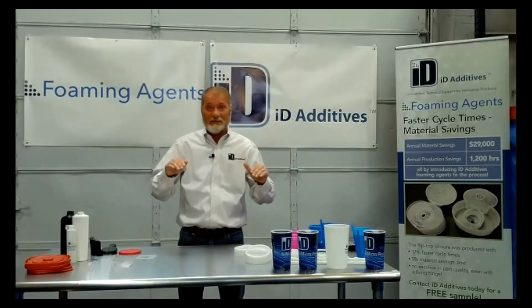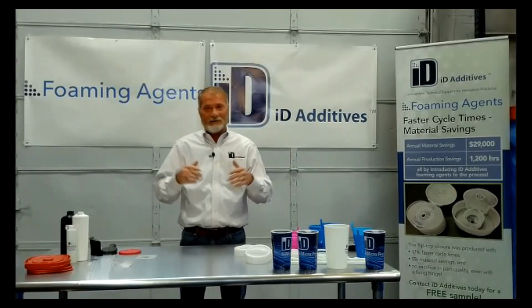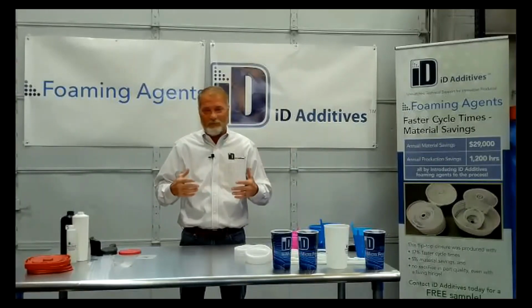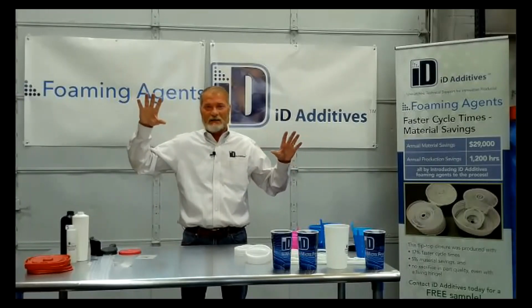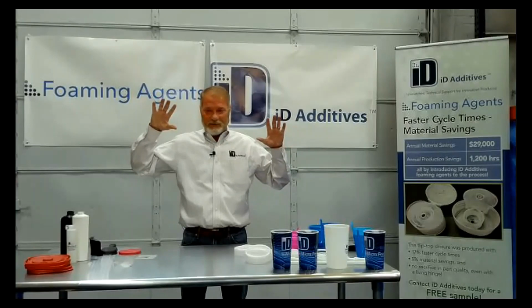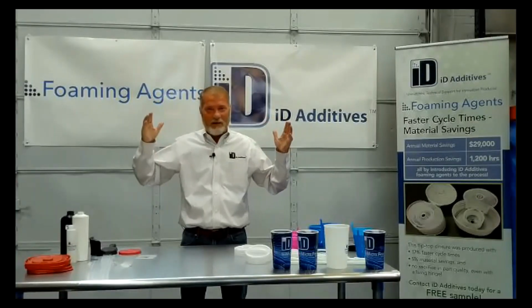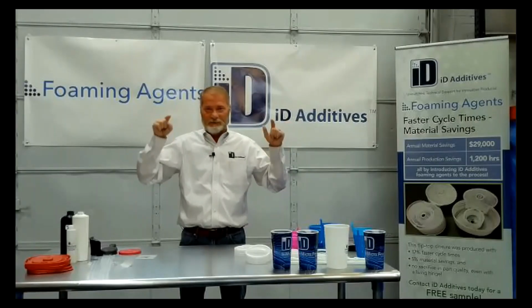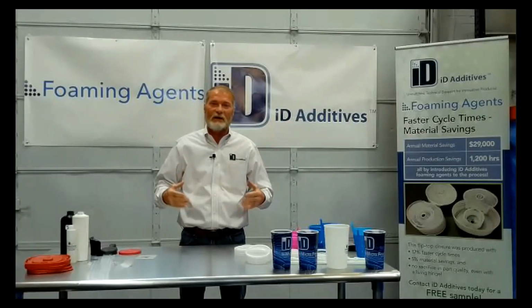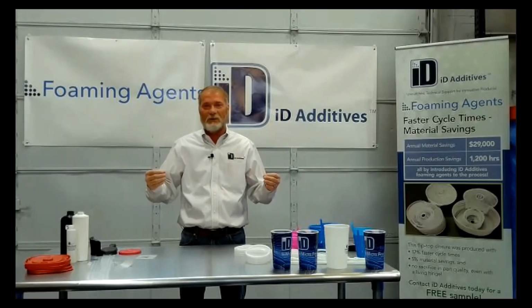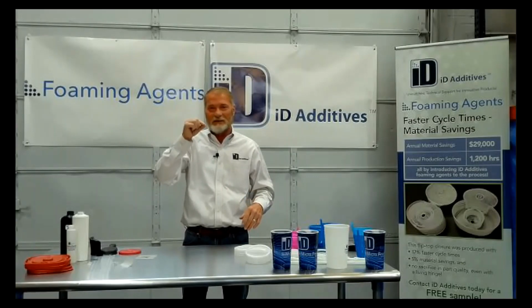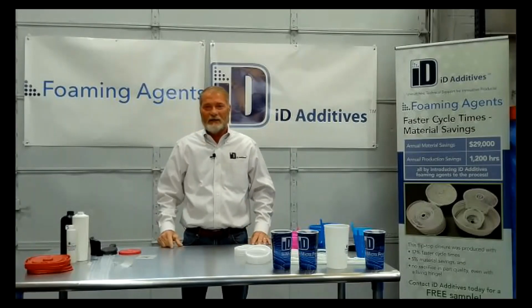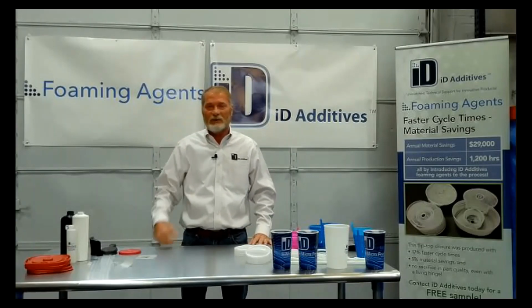If you've got hot tips, a lot of times when you're trying to foam multi-cavities or you've got multi-gates, I've had parts with 48 hot tips on them and drooling, but they needed a more aggressive foaming agent to pull weight out of this particular part. We turned the tips down, kept turning the tips down until there was just a tiny little pud on each gate. And shot to shot, it ran like a champ.